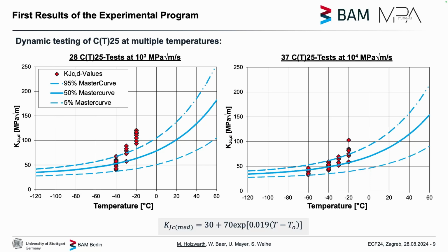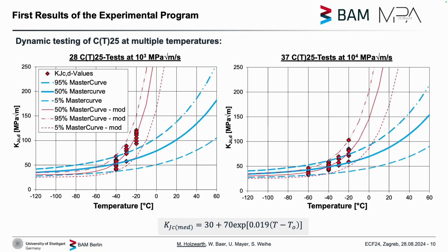And from now on, since our data set is not yet concluded, we are still waiting on the CT50 and the DCT9 results. It's a bit of a more open discussion because the results are just not yet final, so take it with a grain of salt now. For example, what we can do is, this factor 0.019 is for the slope of the master curve. If we fiddle with that a little bit, I don't even quantify it because it's yet work in progress, but we can see we get a way better fit.